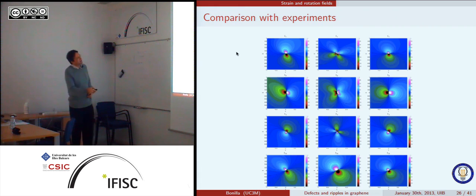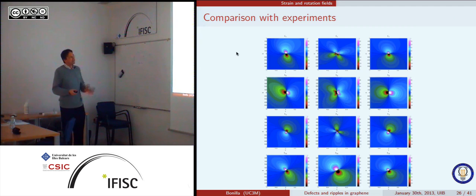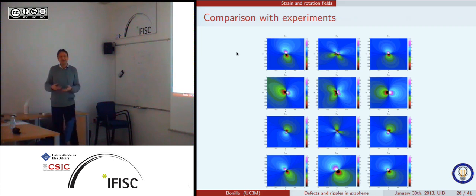So for instance, you see the difference between these. These are the effects of the other dislocation and a group of dislocations that are far apart. So this is half the picture. We didn't show the other one. The way these defects are created by irradiation, you start with a pristine lattice, and what you create has to have an overall Burgers vector equal to 0. So this is why you create these dipoles naturally.